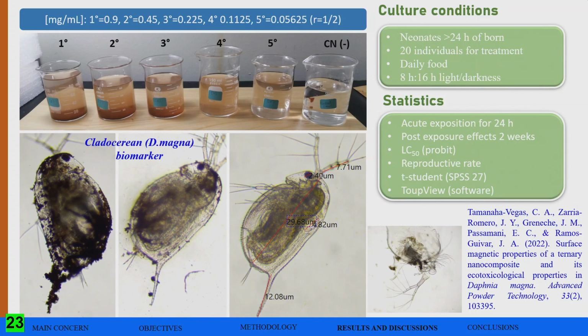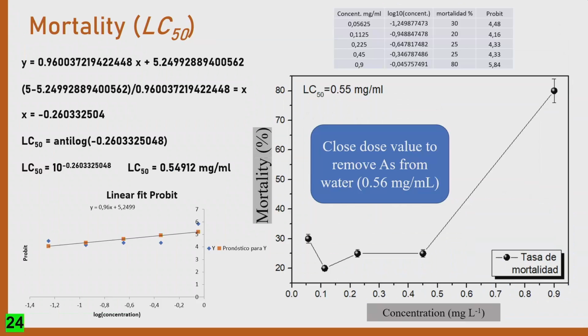So we do that with 20 individuals per treatment. We make a daily feeding. We use a light and darkness ratio of 8 to 16 hours here. And of course, we need some statistical approaches to calculate the lethal dose concentration and the reproduction rate, using Student's t-test and other statistical approaches. So we can use the Probit method here. Here is this famous Probit table to obtain the lethal dose concentration under several doses of maghemite nanoparticles.